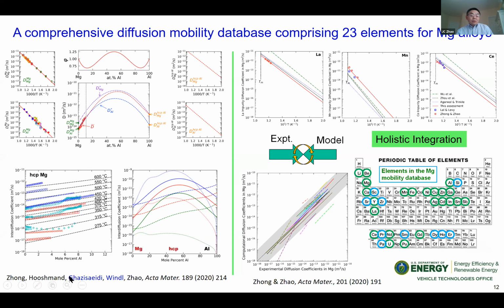We also computed, this is work with Professor Wolfgang Windl and Miriam Zayati at Ohio State when I was there, the metastable phase like HCP aluminum and its self-diffusion coefficient and the impurity diffusion of magnesium in HCP aluminum. There's no way to measure it, right? Because we can compute this data, it's much more reliable than using such a small amount of data to fit the entire binary diffusion coefficient. This is something I'm going to talk about more as I move along. Again, this tries to leverage the good parts of both simulation and experiment to do the best job.